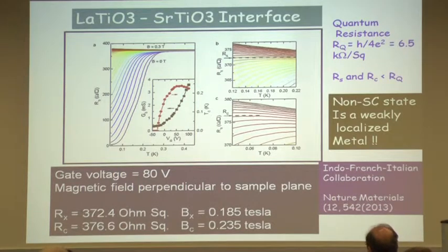So this is the result. This measurement has been done at 80 volts positive gate voltage. This is at zero magnetic field, superconducting transition. And as you keep on applying more and more field, the TC drops. And finally, somewhere here, the sample enters the normal state. But I would like to tell you that if you look at the value of sheet resistance here, it's only about 400 ohm per square. And the quantum resistance for localization is about 6.5 kilo ohm per square. So we are still in the metallic state, although we have gotten rid of the superconductivity.